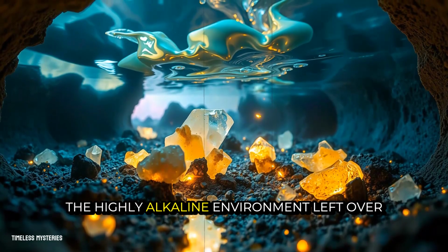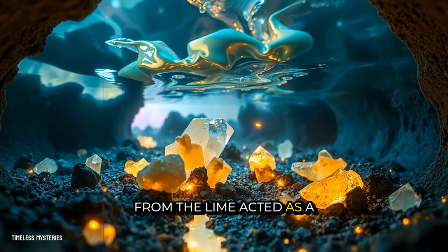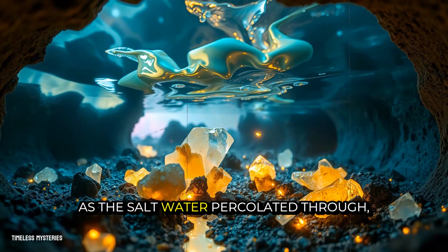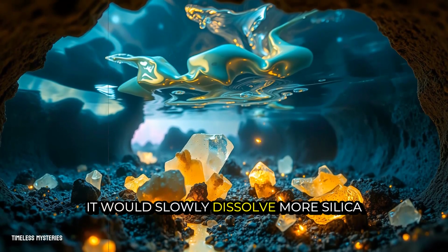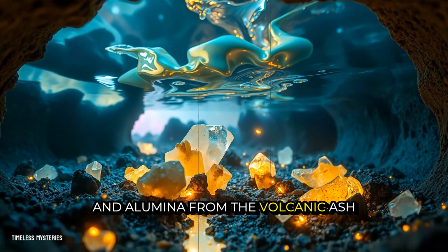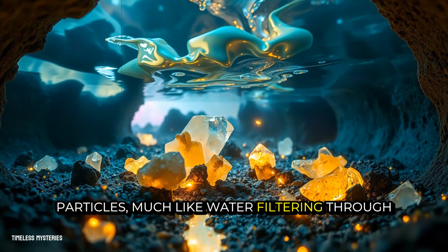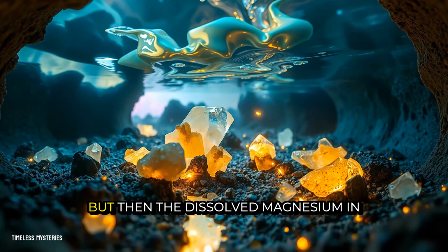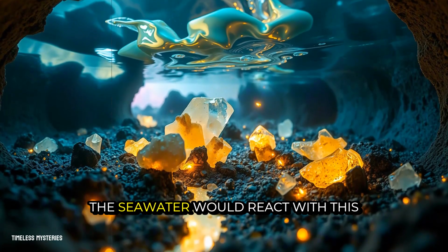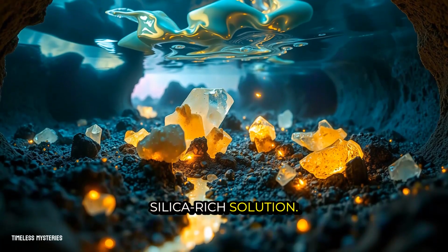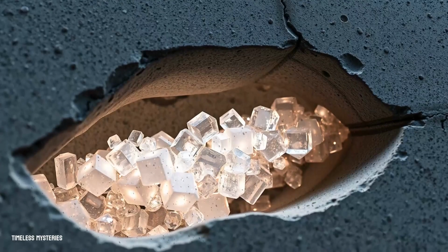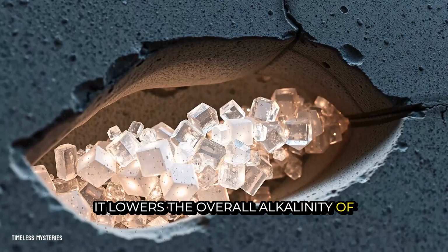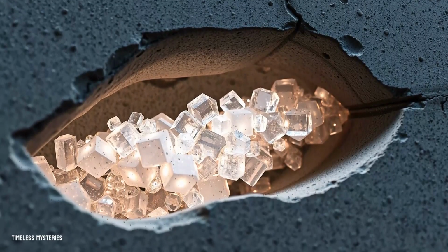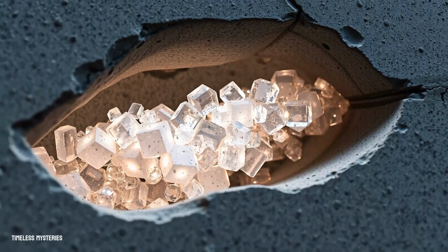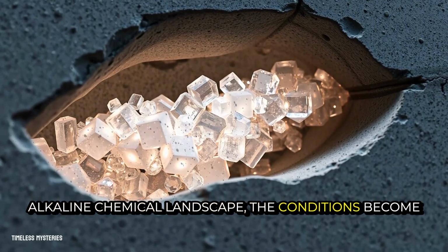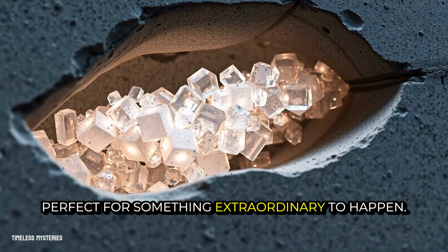The highly alkaline environment left over from the lime acted as a filter. As the salt water percolated through, it would slowly dissolve more silica and alumina from the volcanic ash particles, much like water filtering through coffee grounds. But then, the dissolved magnesium in the seawater would react with this silica-rich solution. This reaction is key. It lowers the overall alkalinity of the concrete's internal environment. And in this new, slightly less alkaline chemical landscape, the conditions become perfect for something extraordinary to happen.